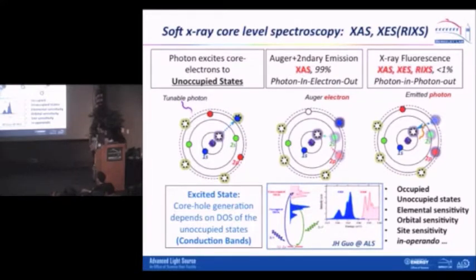So in combination, the absorption tells you the unoccupied conduction band. And when you measure the decay photon, what is the energy of this decay photon coming out? That's the so-called X-ray emission. It tells you the occupied valence band states. And the combination over here is the band gap. I am very sure this diagram is very popular. It was drawn many years ago by Jinghua at the ALS. He's sitting right there.